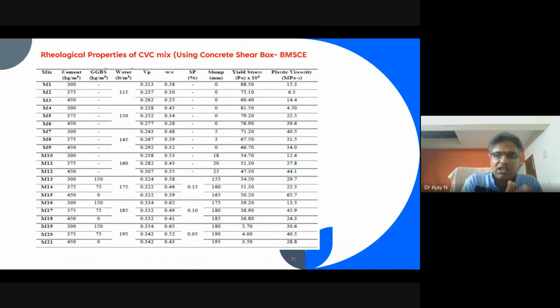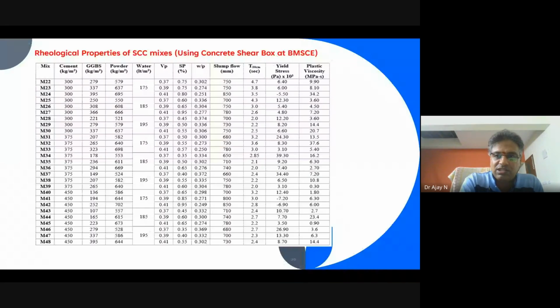The shear box gives all the properties, and you can see the mix differences, because the M1 to M9 mixes show 0 slump, but using these two parameters we can really differentiate the mixes. We applied the same thing to the SCC mixes also. We conducted slump flow, T500, L box, all the tests. In SCC, we have to assess three things: flowing ability, filling ability, and segregation resistance.